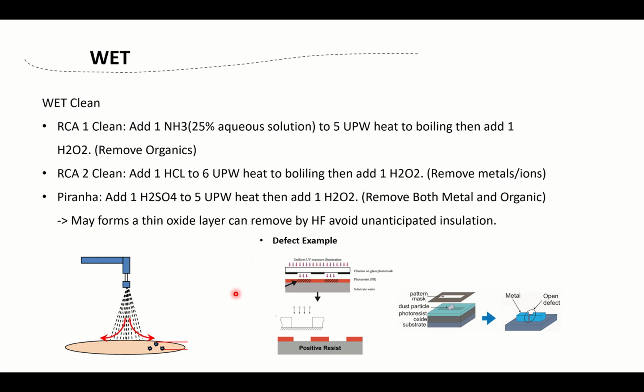For the wet cleaning one page, we want to clean the wafer before we start the process or after the process to remove any impurities. For wet cleaning, we might use ammonia with peroxide to remove organics from the surface, or we can use hydrochloric acid with peroxide to remove metals and ions. Also, in the process they use a lot of piranha solution, which is sulfuric acid with peroxide, and this is really corrosive, which can remove both metal and organics. However, it will form a really thin oxide layer, which can be removed by HF.